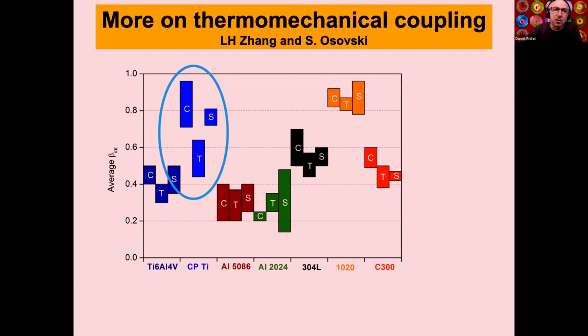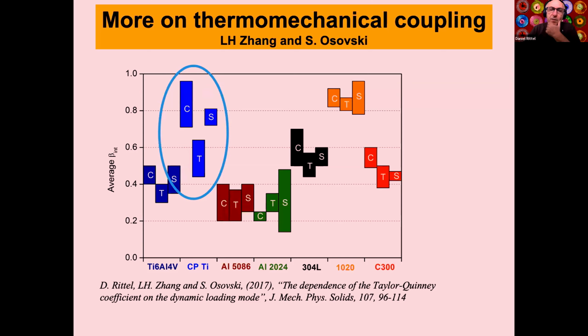So not all materials are symmetrical, and pure titanium is one of them. And that has been noted in the literature in another context of yield surfaces, in the work of Oana Cazacu, for instance, and Frédéric Barlat. So we reported that the Taylor-Quinney coefficient, first of all, is not 0.9 as universally accepted following the pioneering work of Taylor and Quinney. It's not 0.9. It can have various values, smaller values, and that depends on the material and sometimes on the loading mode.